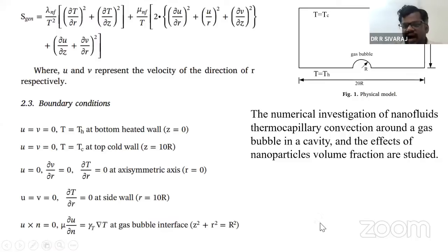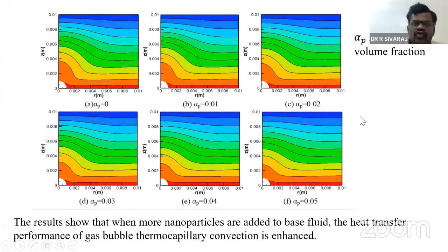The numerical investigation of nanofluid thermocapillary convection around a gas bubble in a cavity, and the effects of nanoparticle volume fraction, are being studied in this. The bottom wall is the hot wall, the top wall is the cold wall, and the gas bubble is here. Now we will see, when we include the suspension of nanoparticles and with only base fluids, how the heat is being removed from the hot wall to give the system better cooling through various values of the nanoparticle volume fraction parameter. This nanoparticle volume fraction is denoted with the parameter alpha p here.